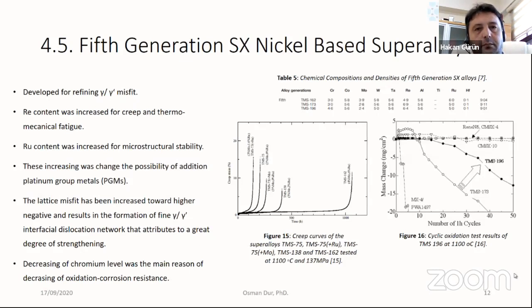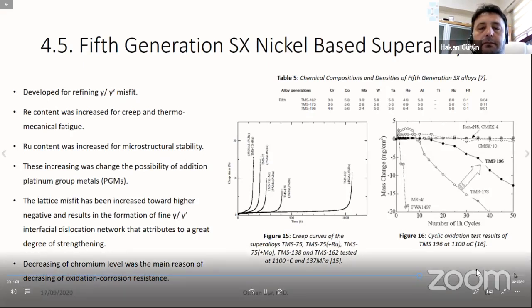The lattice misfit has been increased toward higher negative and results in the formation of a fine gamma over gamma prime interfacial dislocation network that contributes to a great degree of strengthening. Decreasing chromium level was the main reason for decreasing oxidation and corrosion resistance. In this generation, the most important loss was corrosion and oxidation resistance. As you see in the creep figure, TMS-162 is much better than old generations. However, TMS-196 mass change is very high when compared to others.